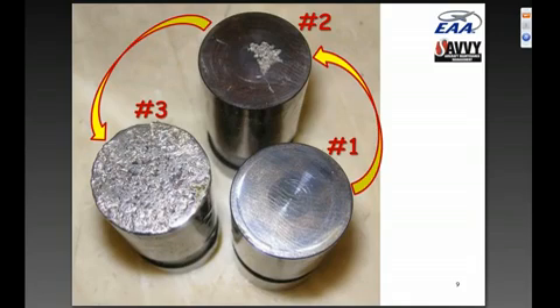That number 2 lobe, as you can see, is partially spalled, and maybe 20% of the surface has been destroyed by the spalling process. And that number 3 lifter is in its sort of final state of destruction, where the entire face of the lifter is spalled. And although these are 3 different lifters, you can almost think of this as a time-lapse sequence of what would happen to that number 1 lifter if it stayed in service and it gradually came apart.